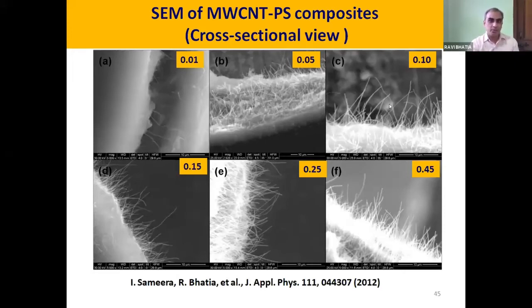There are some protrusions. These are the protrusions, and the number of protrusions increases with the increase of weight fraction of CNT within the composite. So this is a very systematic study that we tried to carry out. We prepared samples of 1 weight% and we cut it. We go to the SEM machine and see whether we have enough protrusions or not.